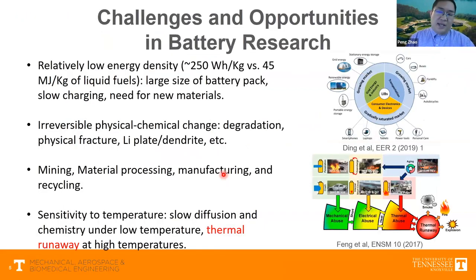So from my understanding, I think that there are 4 primary challenges about lithium-ion battery research. The first one is energy density. If you consider that the state-of-the-art lithium-ion battery has an energy density of about 250 watt-hour per kilogram, that's only about 2% compared with 45 megajoules per kilogram, a typical energy density for gasoline and diesel. So this limits the application for batteries to low to medium duties. And for heavy duty applications, it will basically require a tremendously large battery pack that further aggravates the slow charging issues.